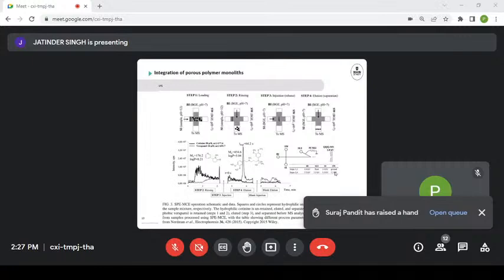Polymer monoliths have also been integrated by other people for other purposes. And here we've got a more advanced functionally integrated device for solid phase extraction. So you can see the gray area is where they cross-linked the monolithic phase. They injected a sample, and the target molecules that were in there adhered to the stationary phase. The ones that didn't have affinity didn't adhere, so they just washed out. Then a rinsing step, where you could check in the mass spectrometer what was going on, but the focused analytes were still sitting here.